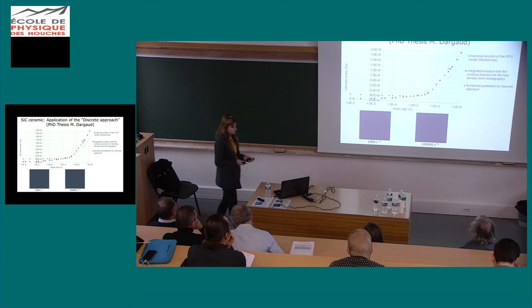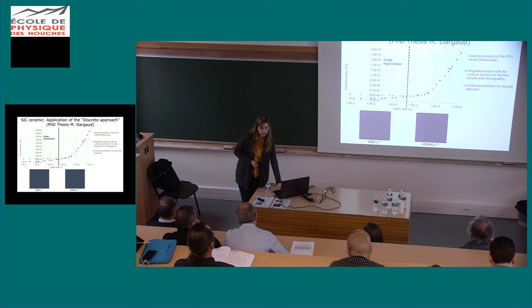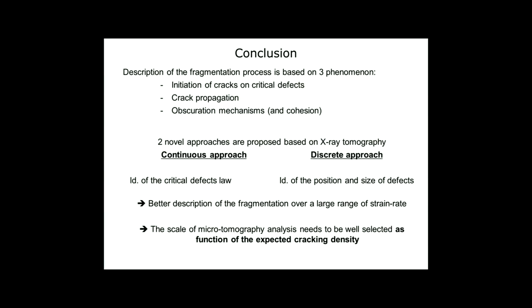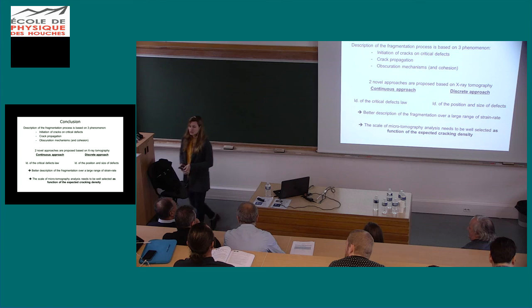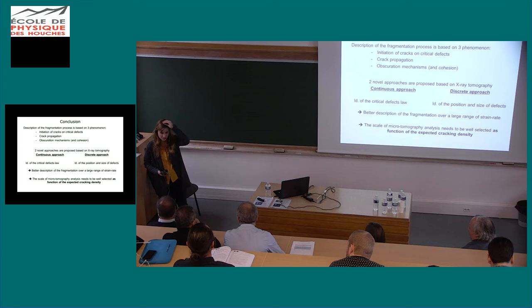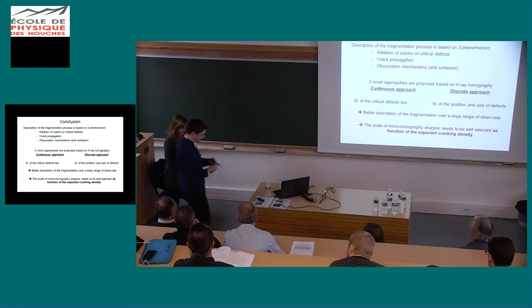Here you have the fits of the discrete approach, the continuous approach, and what is given by the analytical solution of the DFH model. And you have a very, very good fit. On the left side you have a single fragmentation where you initiate only 1 crack, and on the right side you get this multiple intense fragmentation. So it's working very well for the 3 different materials. This is the way to test this approach.